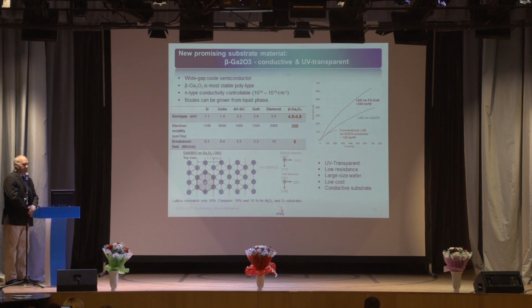A few words about this gallium oxide material. This is a brand new direction, just generated maybe 2 years or 1 year ago, and the direction is on the possibility to use gallium oxide for various optoelectronic applications. Gallium oxide is a wide band gap semiconductor with remarkable properties, rather high electron mobility, but what is important, with a very high breakdown field. The breakdown electric field is somehow very close to that of diamond.